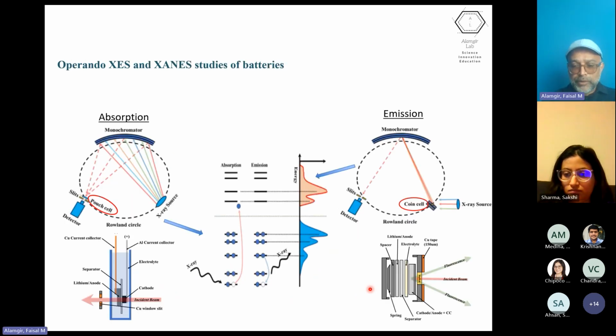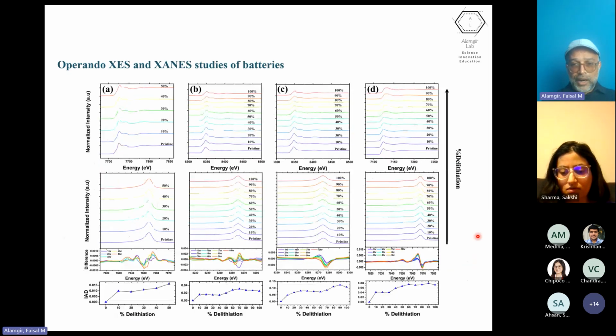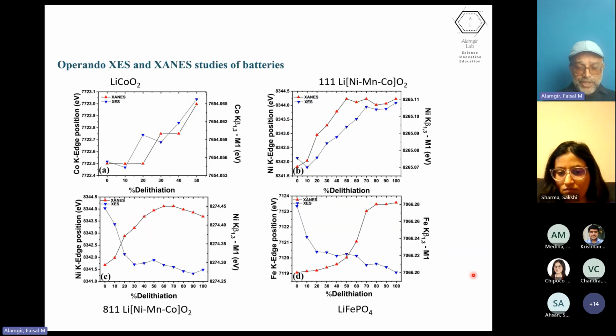We've used this kind of work to study battery chemistry in a real battery under operating conditions, and here is a large array of data. Of course, we're so zoomed out you cannot see the details of what is happening. But if you look at the differential measurements here, you can see that there's a lot of changes that are being picked up. Those changes can be used for tracking the state of charge of the battery. One of the first studies we did was to benchmark X-ray emission as an analytical tool for following the battery chemistry of a battery.